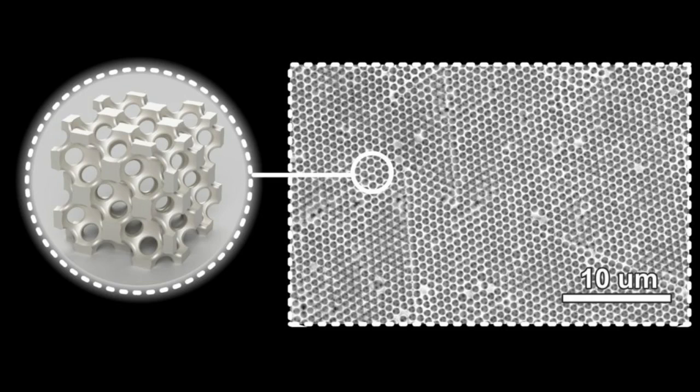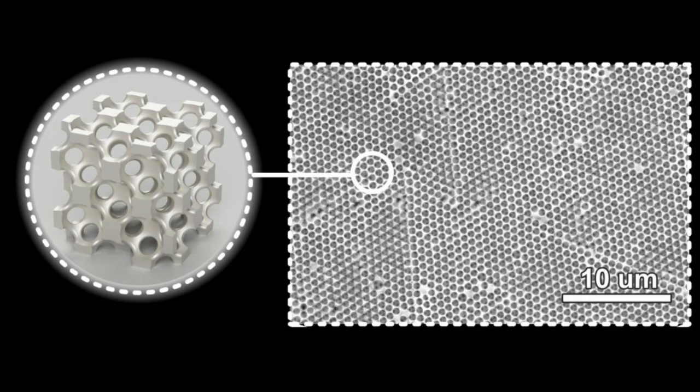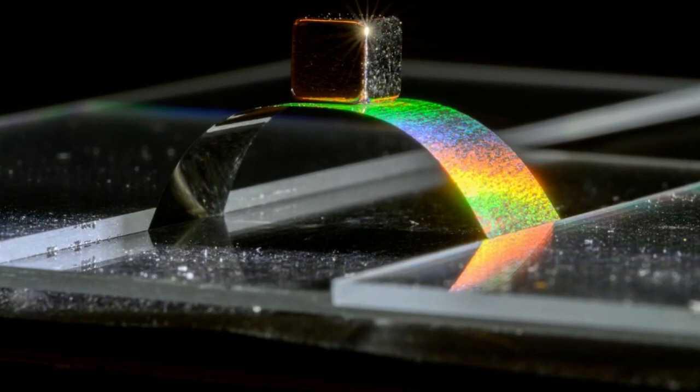However, if there are any places where the spheres' regular stacking pattern is disturbed, the nickel will fill those gaps, producing an inverted crack when the template is removed. The standard way to build these materials is to start with a nanoparticle solution and evaporate the water until the particles are dry and regularly stacked. The challenge is that the surface forces of water are so strong that they rip these particles apart and form cracks, just like cracks that form in drying sand.